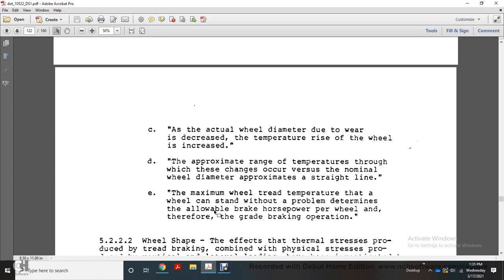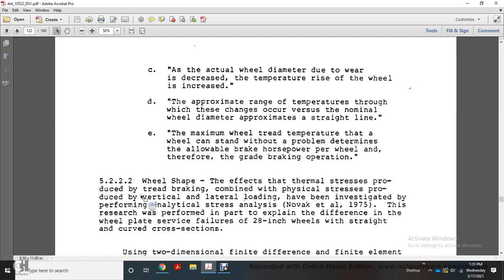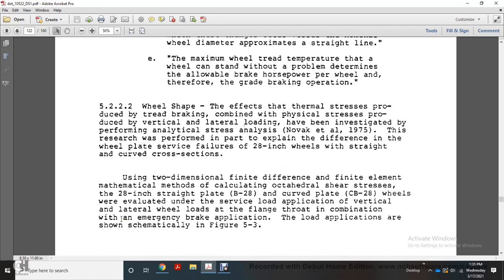Maximum wheel tread temperature that a wheel can stand without a problem determines the allowable brake horsepower per wheel. Therefore, the effect of wheel shape on the thermal stress produced by tread braking, combined with the physical stress produced by vertical and lateral loading, has been investigated. Analytical stress analysis in this research is performed in part to explain the difference in wheel plate failure of the 28-inch wheel with straight and curved cross sections, using a two-dimensional finite element mathematical method of calculating